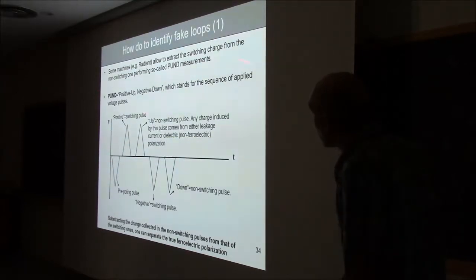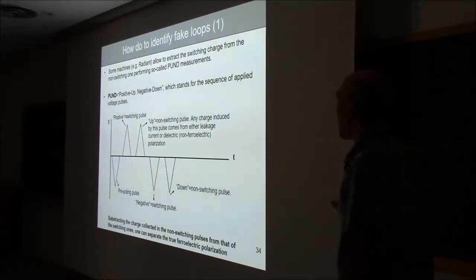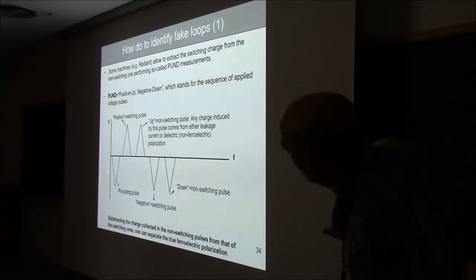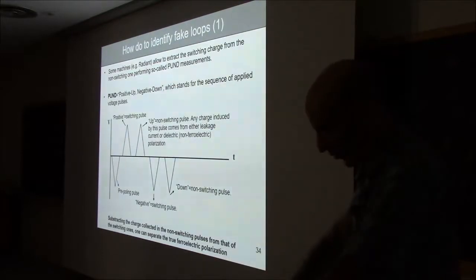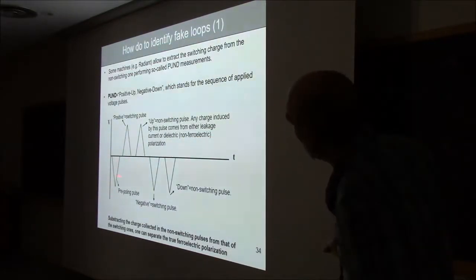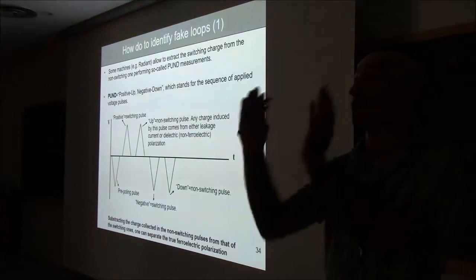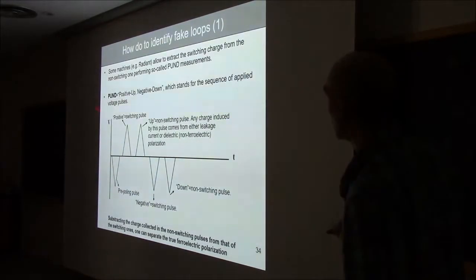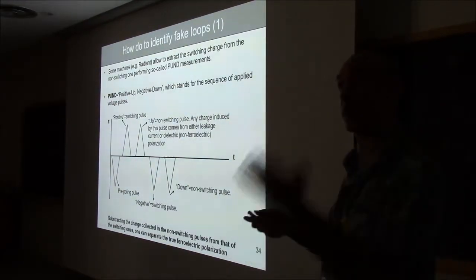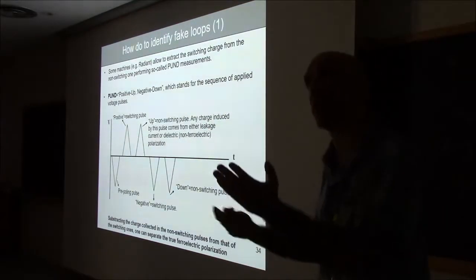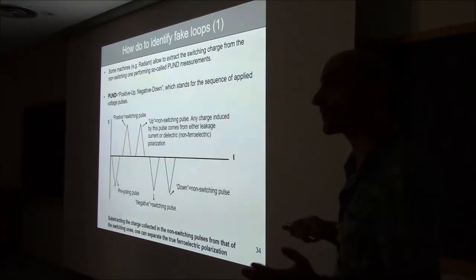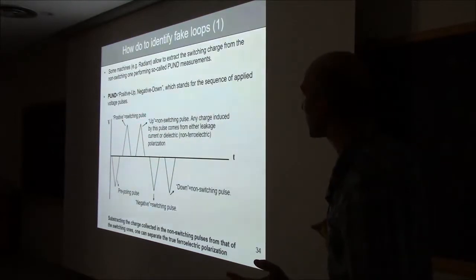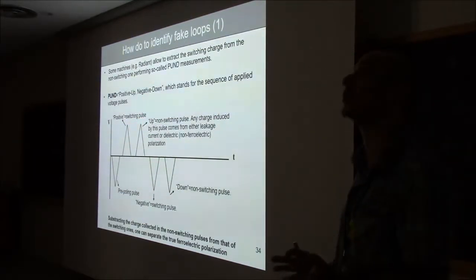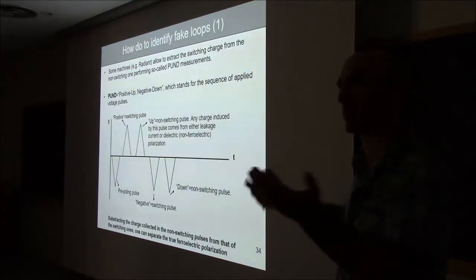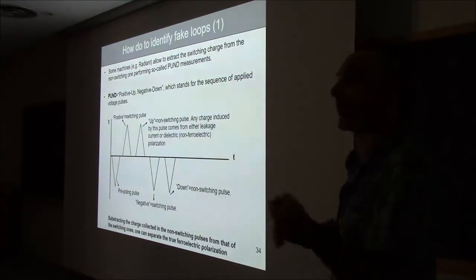One way, if you have the Radiant black box, it's called the PUND measurement, positive up, negative down. So what you do is you apply a negative voltage to pull everything pointing down. Then you apply a positive voltage to switch it up, and you measure the charge when you switch. Then you apply another positive pulse, and you measure the charge again. Now, because this has been switched, any charge that you measure on this second loop cannot be due to switching. It will be all the rubbish. It will be all the leakage. It will be the dielectric contribution.